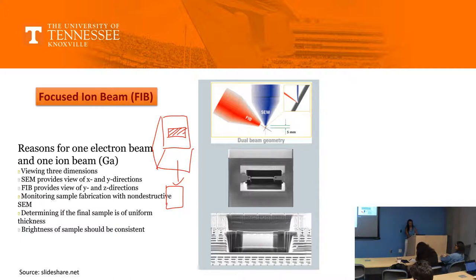Why is it important? Because you are putting your needle here. There would be a needle that would be coming here and attaching to your material. This would be a platinum needle that you would bring. And then you would start making a trench here and it gets separated. Now, why do you have to make it thin? Not extremely thin. Right now it should be around 250 nanometer at least. And when you put it on the needle, then you do a final thinning and that would reduce the material to 100 nanometer, right? So why at this stage are you doing 250 nanometer while it is still attached to the needle?